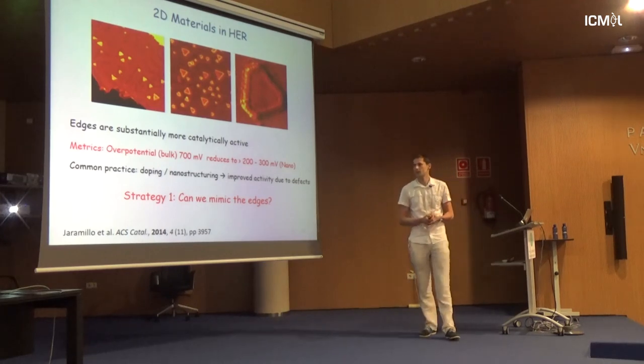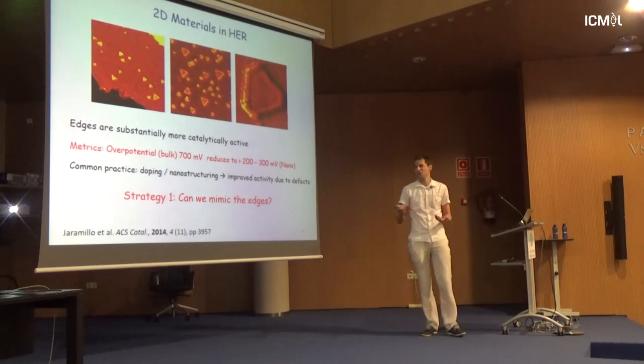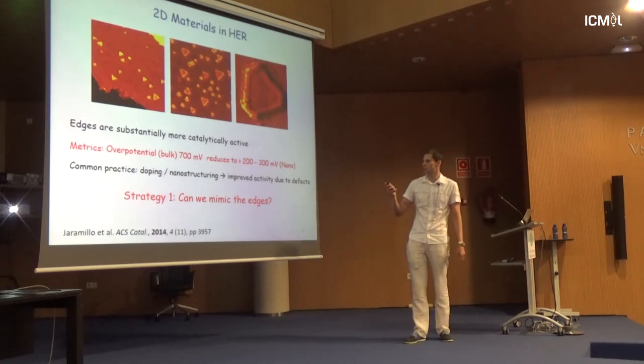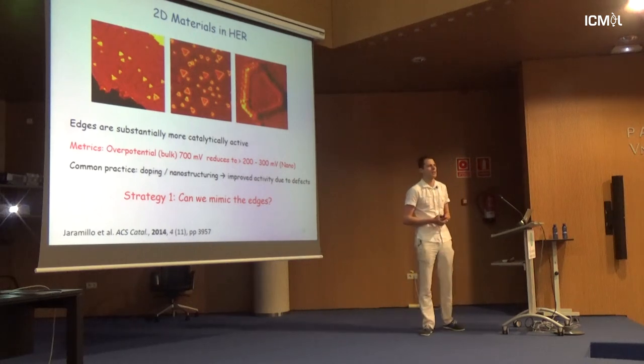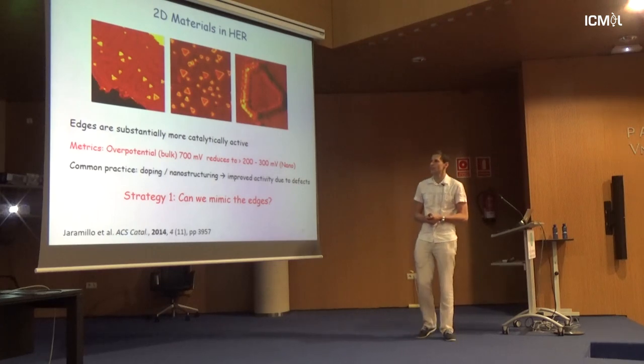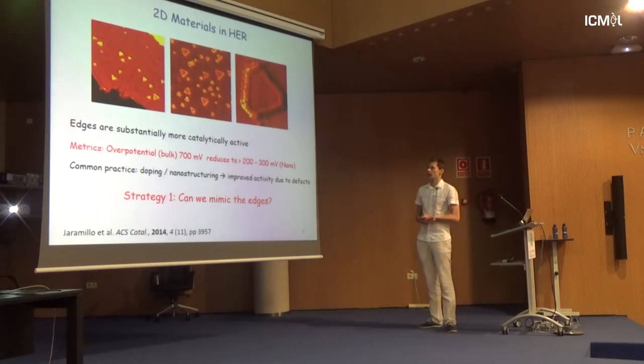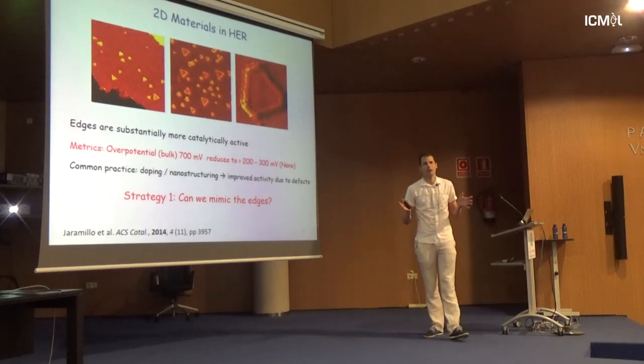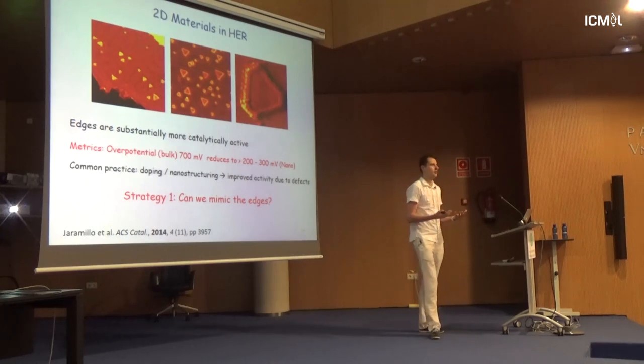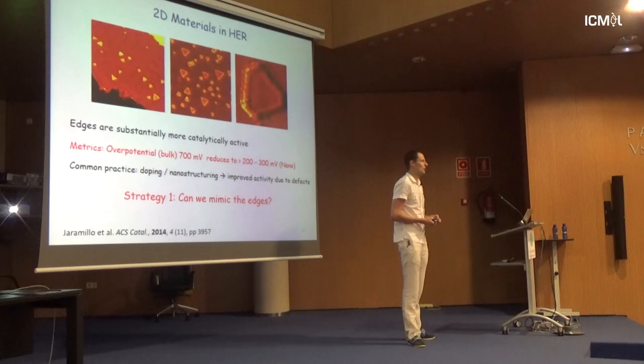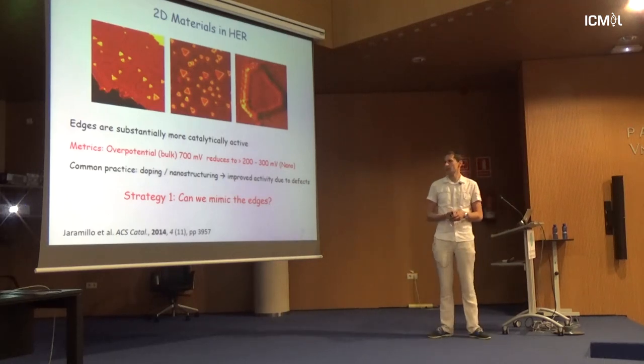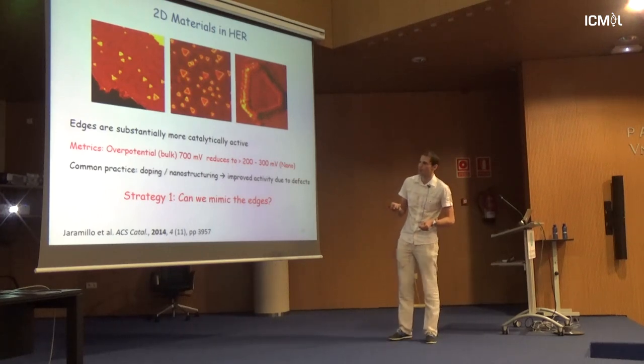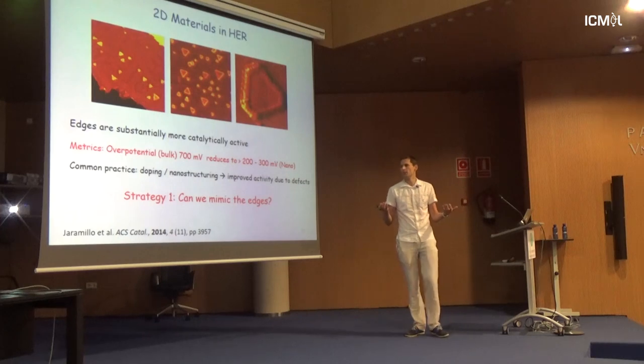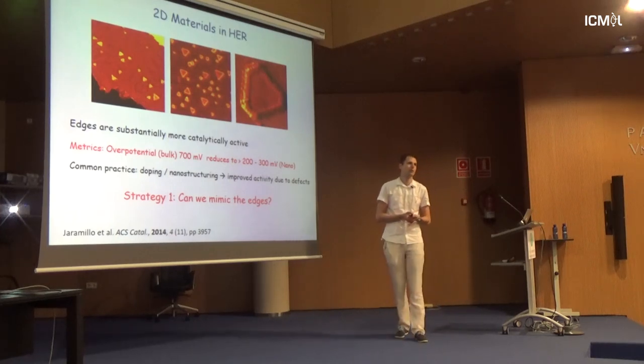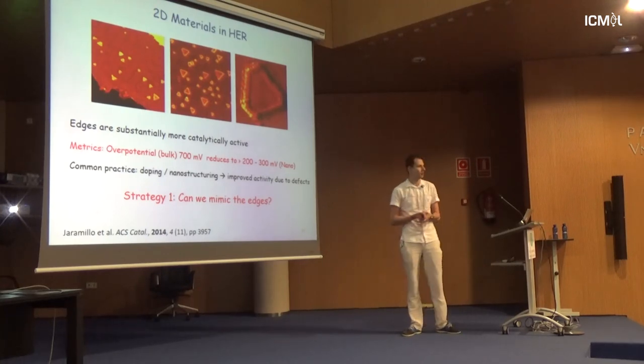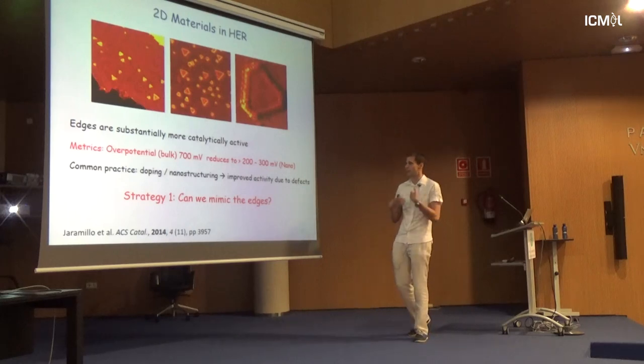And what they very, very convincingly showed, and this is an absolutely epic paper that everyone cites for absolutely good reason, is that the edges are substantially more catalytically active in the case of two-dimensional materials. And this has a dramatic effect when you design your electrocatalyst. So the typical approach, if you read the papers on electrocatalysts, is that nano is good, so we should go nano. And this is a very reasonable approach because if we compare the overpotential, the metric, in bulk, molybdenum sulfide will show you 700 millivolts, rubbish. But when it is reduced, it's almost three times lower. So you can improve it quite substantially.